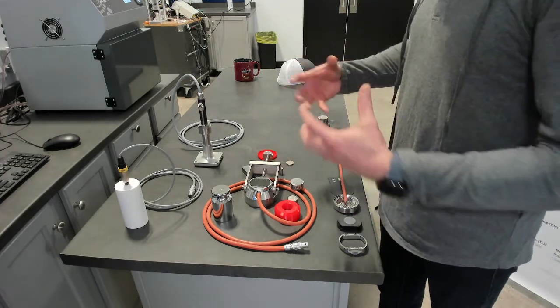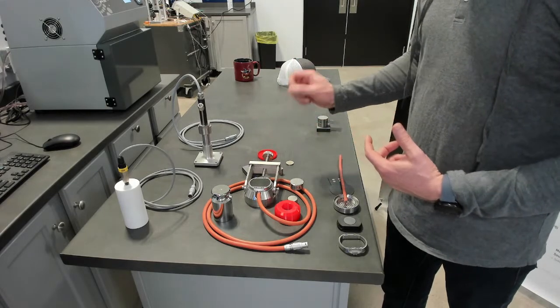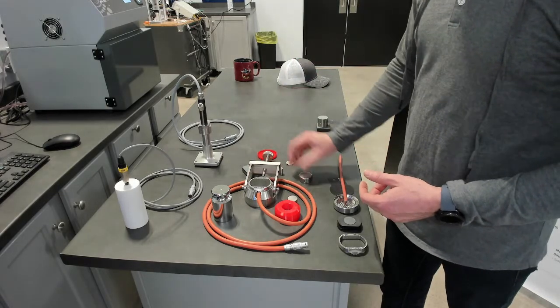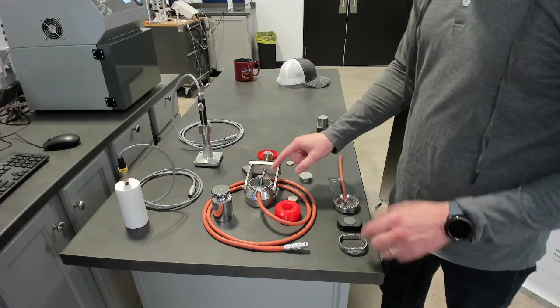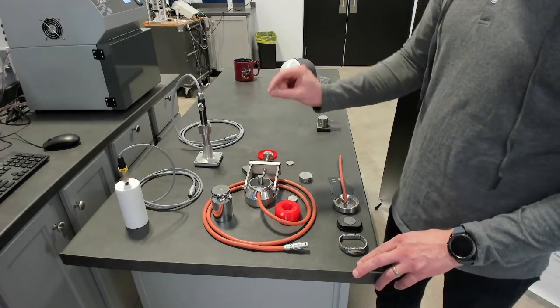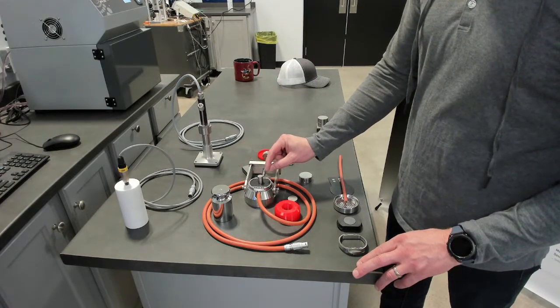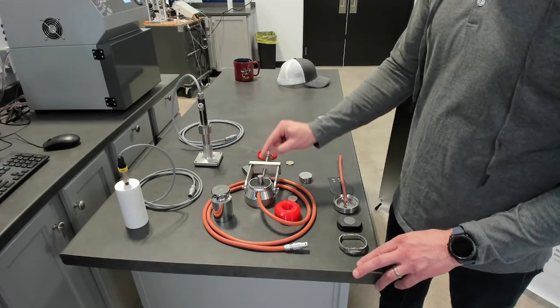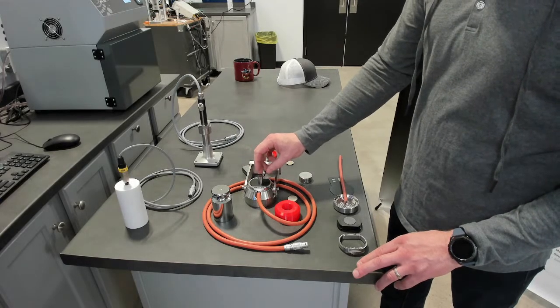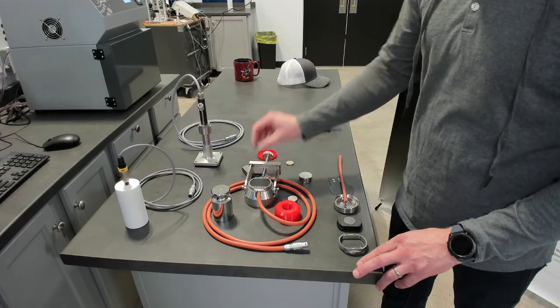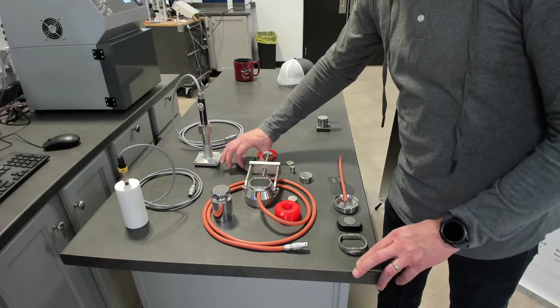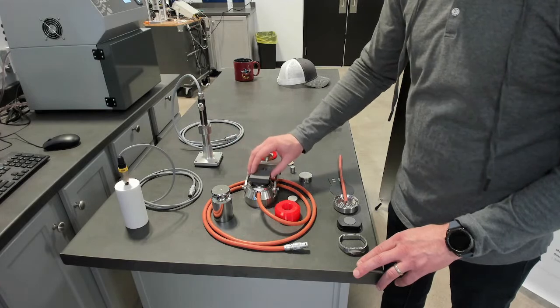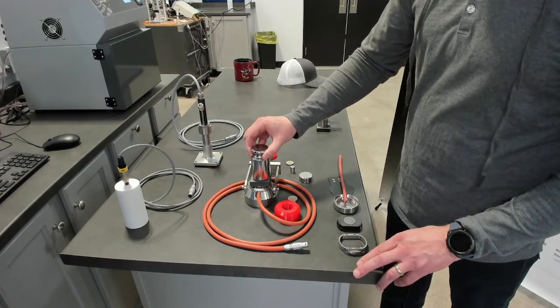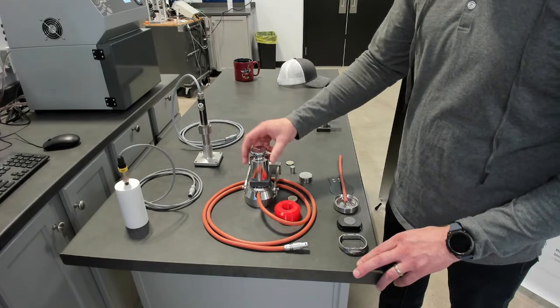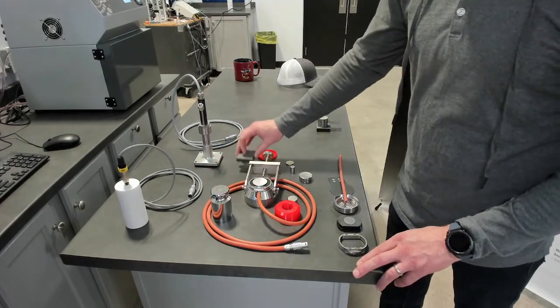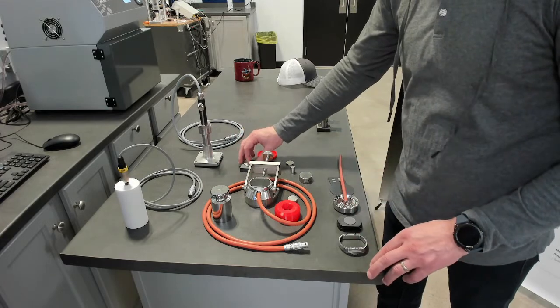And to pack as much punch in that, we added additional modules in addition to bulk. So you have 1D. This takes advantage of when you have a sample that's taller than it is big radially; it takes advantage of that direction to measure along the length of an elongated shape for thermal conductivity and thermal diffusivity. So it includes the 1D module as well as the slab module. Again, these are verification samples that come with the sensor. So that's the configuration for slab, and you already saw the configuration for 1D and bulk.